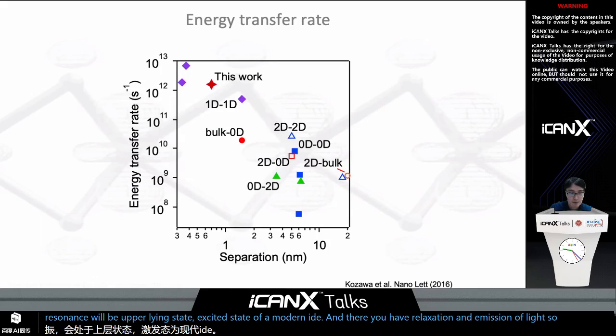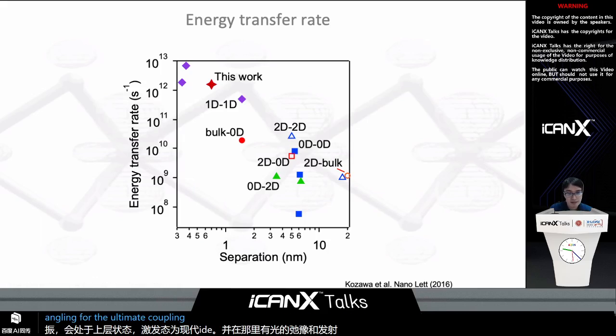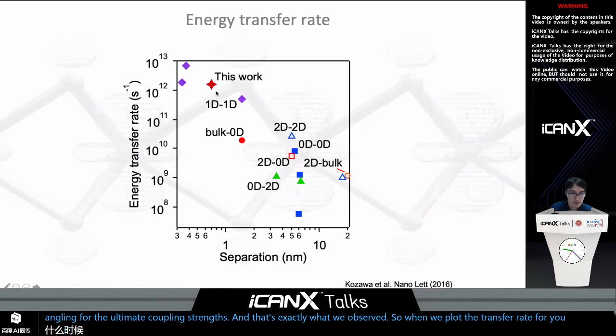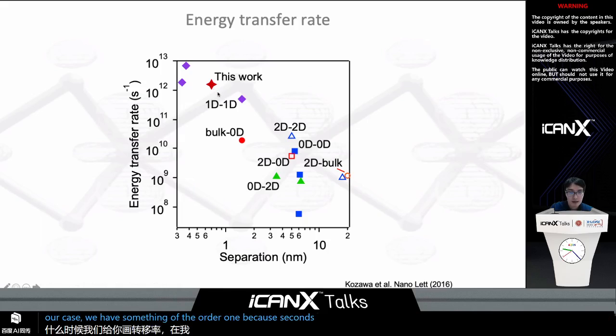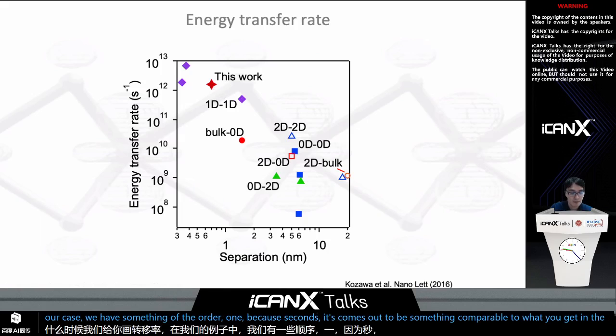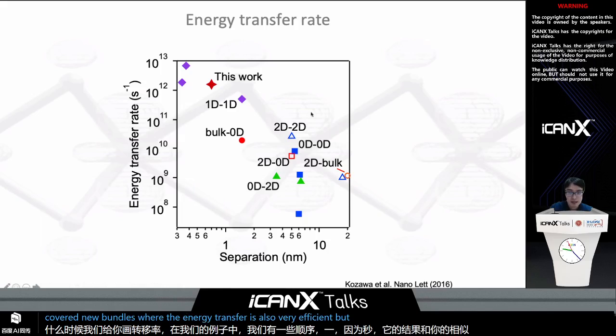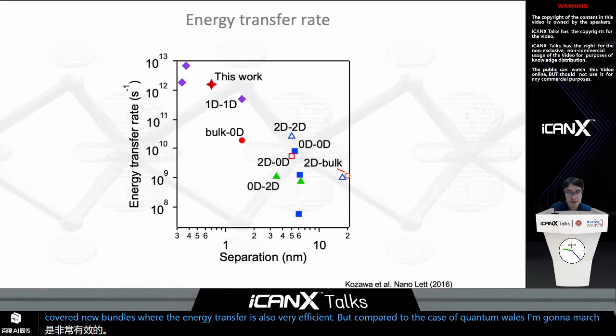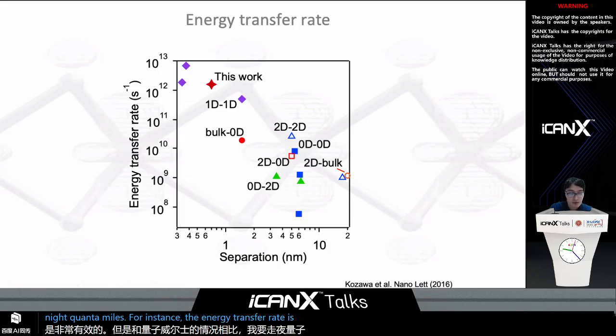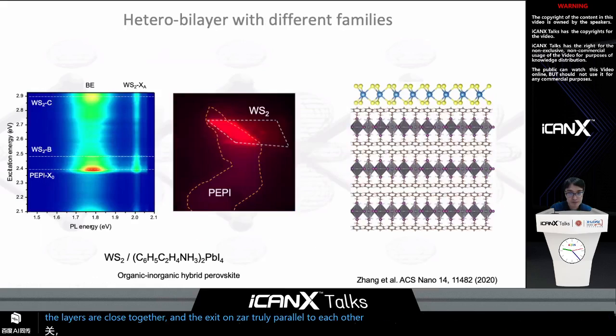So we were aiming for the ultimate coupling strength, and that's exactly what we observed. When we plot the energy transfer rate, in our case we have something of the order of 1 picosecond. It comes out comparable to what you get in carbon nanotube bundles, where the energy transfer is also very efficient. But compared to gallium arsenide quantum wells, for instance, the energy transfer rate is about 2 orders of magnitude higher. And this is solely related to the fact that the layers are close together and the excitons are truly parallel to each other.